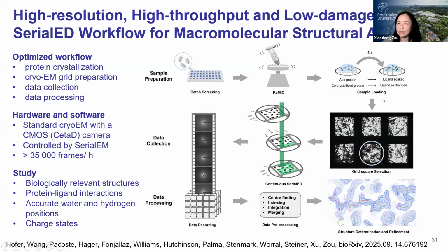You can look at the grid squares to collect serial electron diffraction data using continuous stage movement, and you get a lot of data. Then you can merge the data, do integration, to finally get the structure. So all these workflows are well developed. Now we can optimize protein crystallization, cryo-EM sample grid preparation, data collection, and data processing.